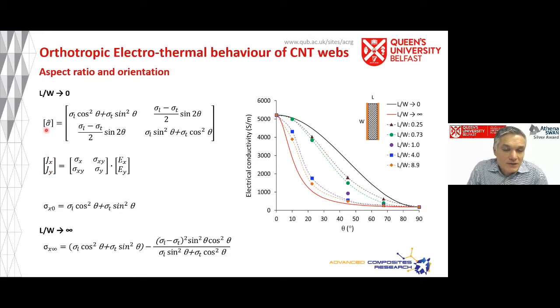So this is now we are trying to predict the conductivity as a function of orientation of that web. Because the web is so thin, by the way, we consider it as a two-dimensional material, and we've got our current density here. This is our conductivity tensor, conductivity matrix, and this is our electric field. And what you will note is that if I look at a sample here, if what I've called my length here is very small, as opposed to that length being very large, or the aspect ratio approaching infinity, the conductivity as a function of angle is different.